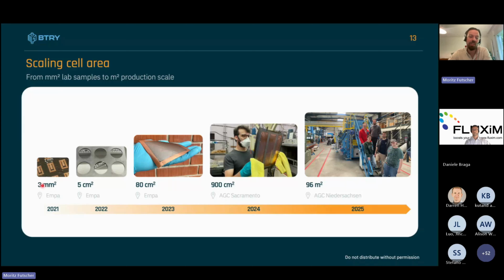And here you can see our journey. Initially at EMPA, we pushed up to roughly 100 square centimeters, which is the maximum which we can do at EMPA. And then immediately we had to switch to larger systems, in this case rented systems, where we are now at a roll-to-roll system in Germany, and you see the machine here, where we can deposit on very large areas.